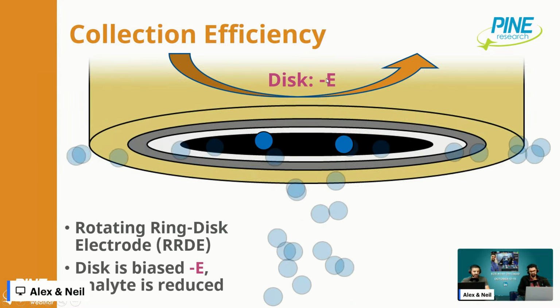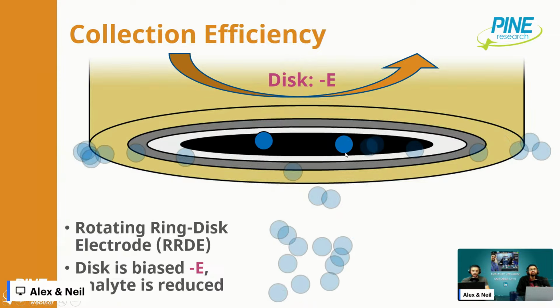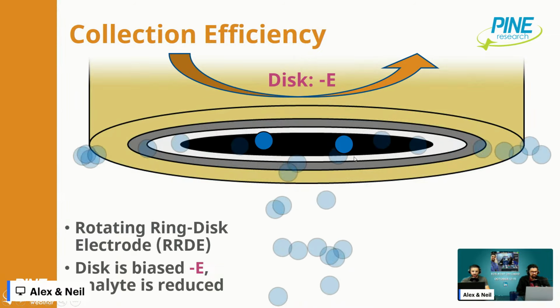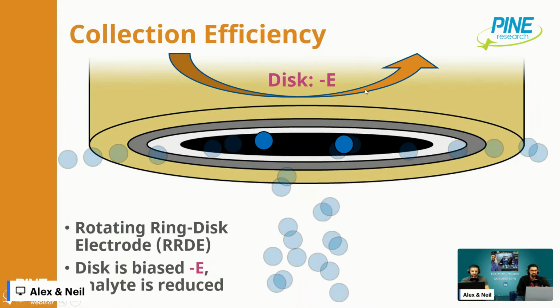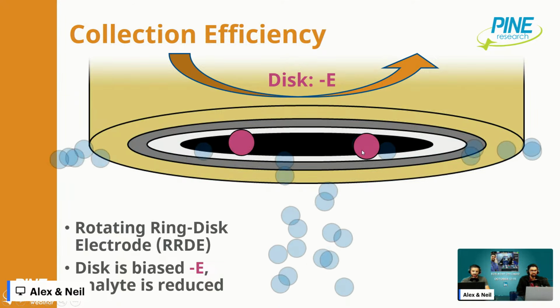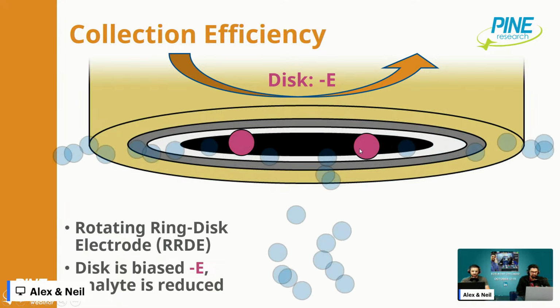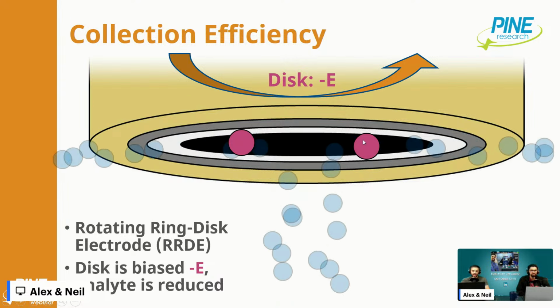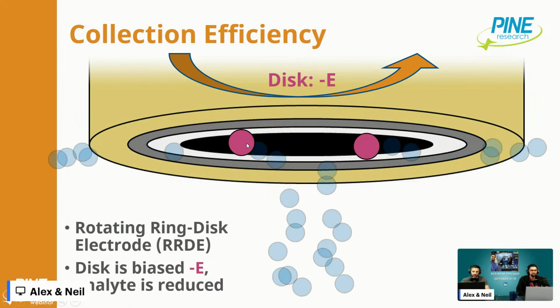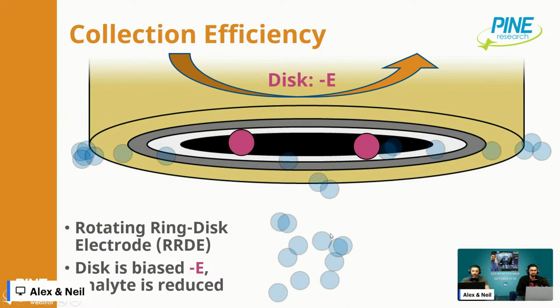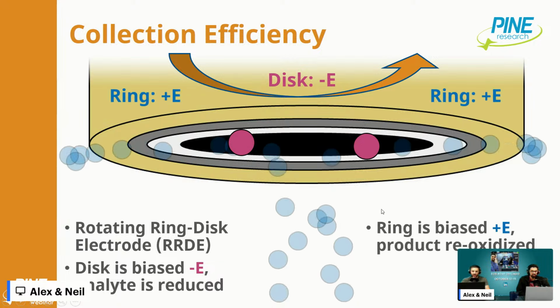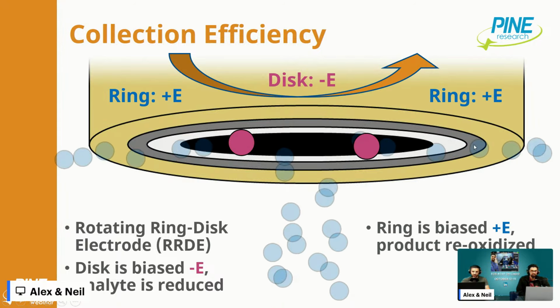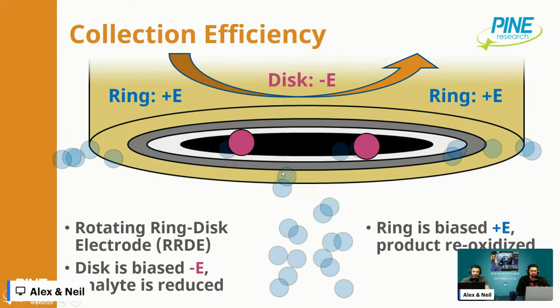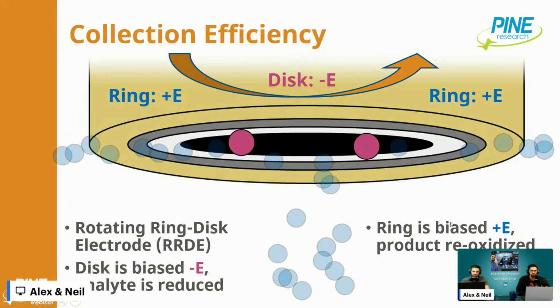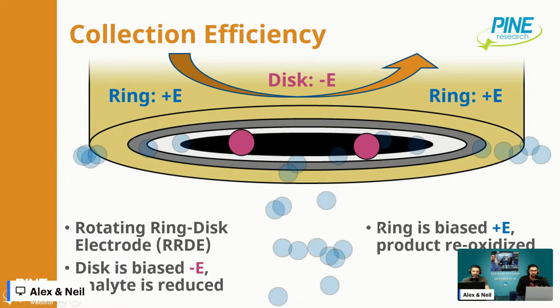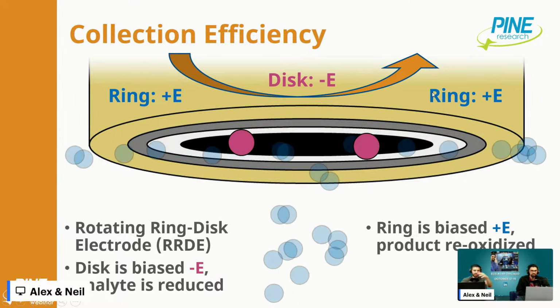I can apply a negative potential, for instance, and that will cause the blue species A to reduce to a pink species, whatever this is. So this is just some reduction reaction. So when that hits the electrode surface, that's what will happen. And then what I can do is I have this ring electrode. This is the second R in RRDE, the ring disc electrode. So I can bias my ring at a positive potential.